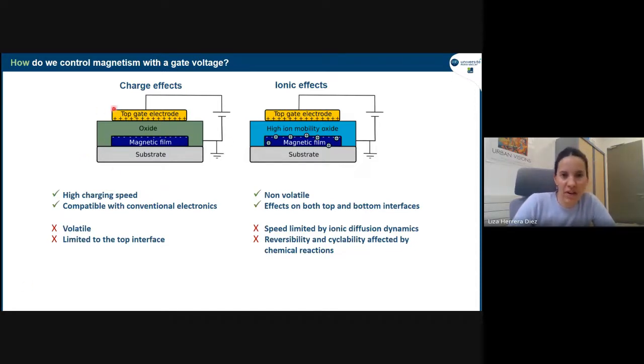What you do here is you have a device that looks like this. You have your magnetic film, an oxide, and a top electrode. Then you apply a voltage between your magnetic film and your top electrode, and you basically charge this capacitor, and you get charges at the surfaces of your two electrodes. One of them is your magnetic film. The trick here is that the magnetic film is a nanostructure. We know that changes in charge accumulation at the interface can be very important for the magnetic properties. For example, we have materials with perpendicular magnetic anisotropy. We know that this perpendicular magnetic anisotropy is seated at the interface. It's an interface effect. So if we can control the charge accumulation at the interface, then we have good chances of actually getting an effect on magnetism.